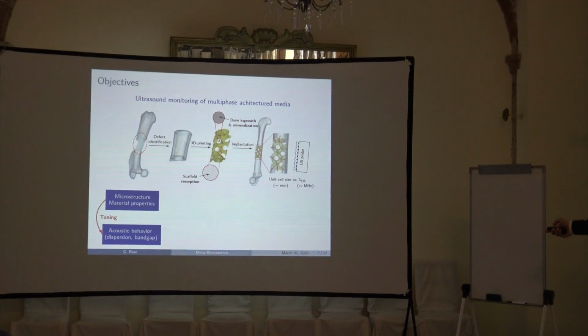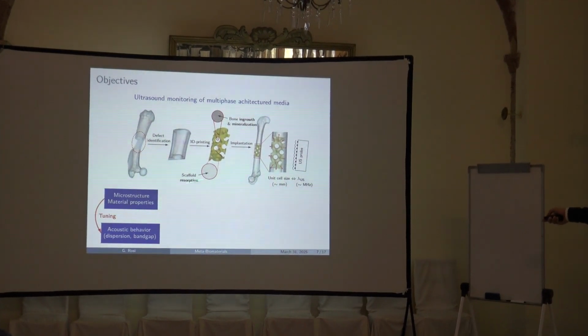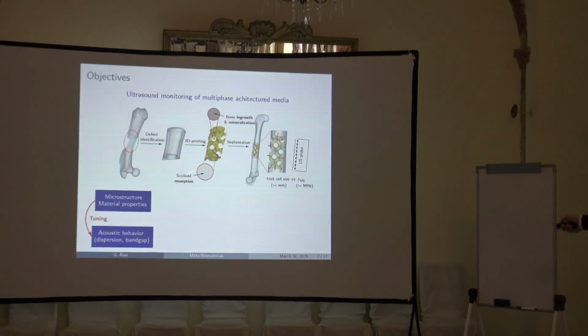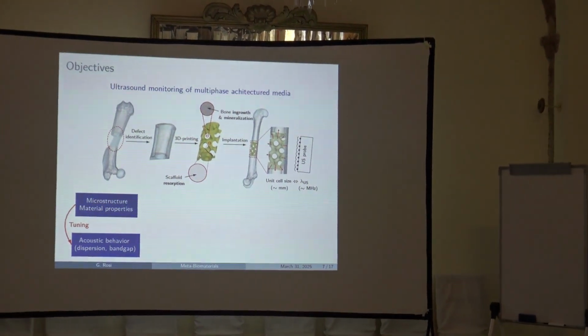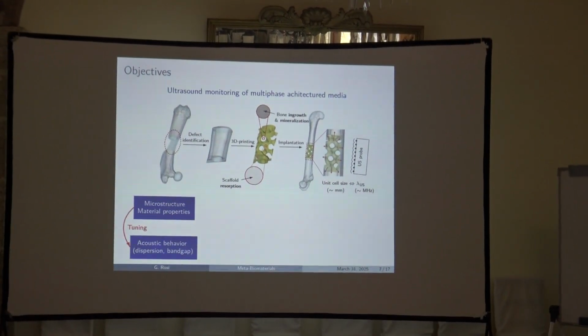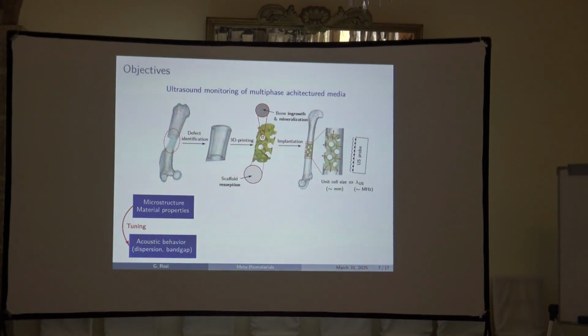We want to put an ultrasonic probe and be able to test the material in a non-destructive fashion. And in order to do that, we want to tune the microstructure and mechanical properties of this implant, to tune its acoustic behavior and create some kind of acoustic signature, which we suppose to be proportional to the feature we want to follow, post-integration, for instance. And we want to do monitoring by following this quantity.